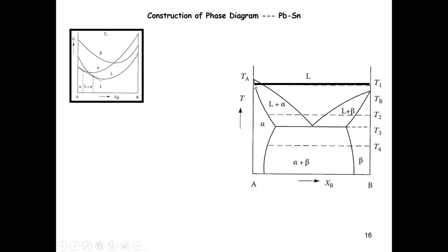So you have this region to be the alpha phase, and in this very narrow region, probably from, I would say, 5% to maybe 15%, like here, you have coexistence. And then for larger composition, if you keep on increasing, the liquid phase is going to be stable, right? So this black line corresponds to this free energy analysis, and even for this temperature, you have three different phase regions: single phase alpha, alpha plus liquid coexistence, and the liquid. Okay, so that's the same thing.